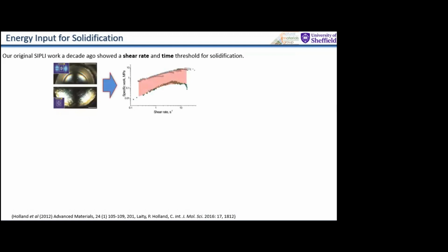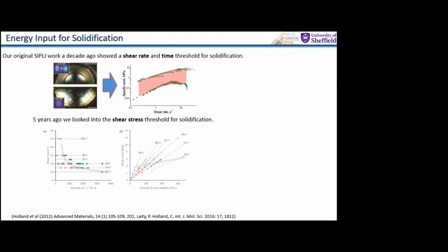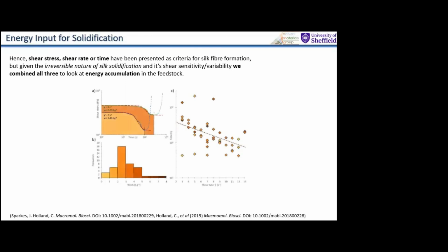So our original work, a decade ago now, showed that you basically need to shear it fast enough for long enough in order to cause it to solidify. And 5 years ago, we found it's not just about how fast and how long you spin it, but also how much force you put into it. So how hard do you mix it in order to cause it to solidify? But what we found is that you need a combination of all three. You need to flow it fast enough and hard enough in order to build up enough energy in the system to stretch those proteins and to get them to accumulate energy and transform from a liquid into a solid.